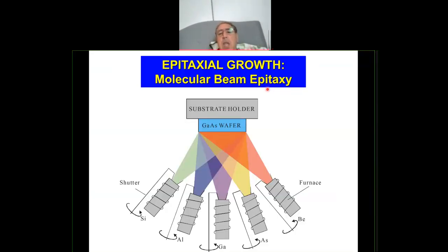So what is molecular beam epitaxy? This is one of the techniques which made a big difference, and as I said in my introduction, it has resulted in several Nobel Prizes for devices grown by this technique. It's a very simple technique. Molecular beam epitaxy is no more than an evaporation technique, but this evaporation is made under ultra high vacuum conditions. Atmospheric pressure is about 760 torr, say 1000 torr. But in this machine, the pressure is 10 to the minus 11 torr. So that's about 10 to the 14 times smaller than in the atmosphere. That means you have practically no impurities or gases inside the chamber where the evaporation takes place, so you get a very pure film.